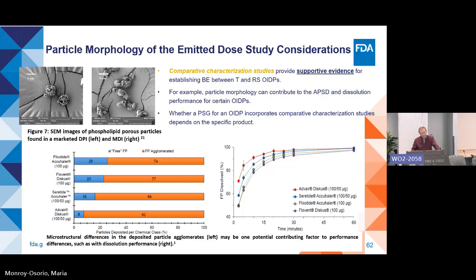And the figure on the left shows the results of a particle morphology study. It indicates that the four different products have different amounts of free fluticasone propionate, or the API agglomerated with the lactose. And these different levels of agglomeration can be detected by the dissolution study shown on the right, with the highest agglomeration showing the slowest dissolution rate.